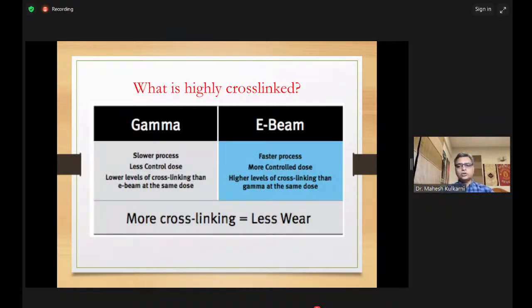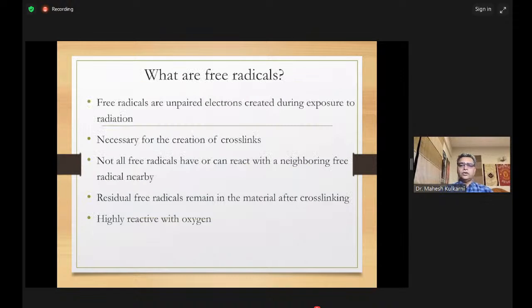So you can see, comparing gamma irradiation and electron beam irradiation, gamma irradiation is a slower process as compared to electron beam irradiation. There is less control of dose with gamma irradiation as compared to electron beam. But gamma irradiation will have lower levels of cross-linking than electron beam irradiation for the same dose. And you need to understand the more the cross-linking, the less is the wear for that material.